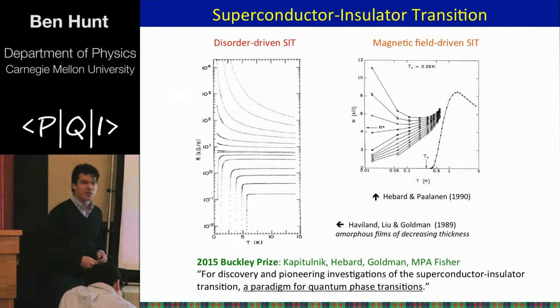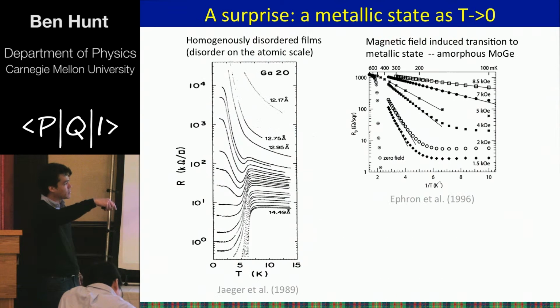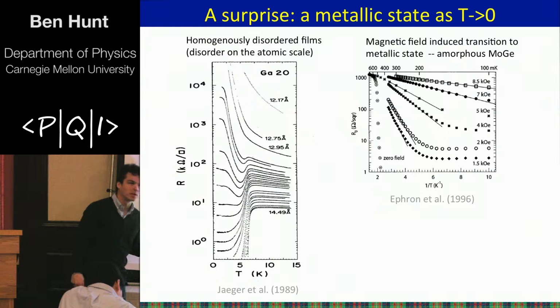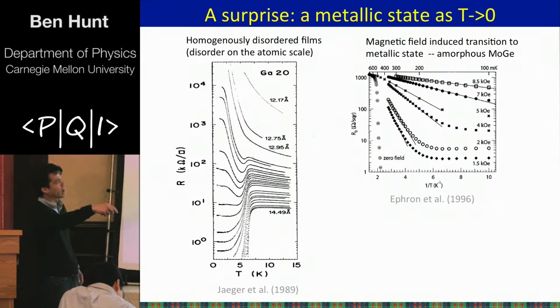What gets kind of brushed under the rug, though, is that actually at the same time as discovering this superconductor insulator transition, in some films, what they would actually see is a very, very large range of not superconductor or insulator, but a metallic phase as t goes to 0. And this was actually sort of rediscovered in the 1990s in Stanford and other places by Aharon Kapitulnik's group in amorphous films of molybdenum germanium.